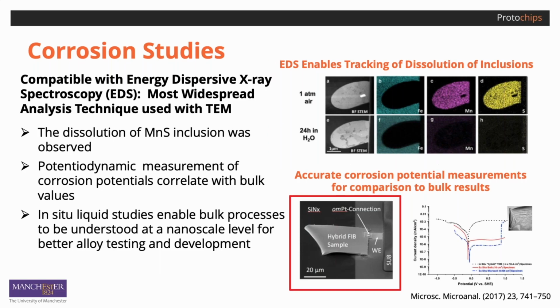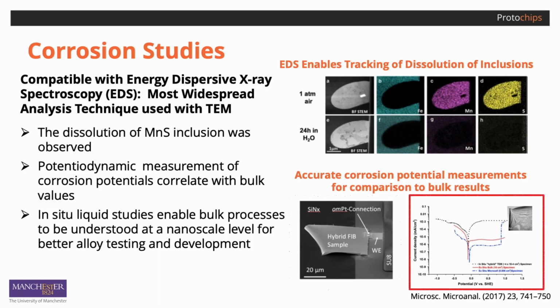An FIB section of type 304 austenitic stainless steel alloy is shown attached to the working electrode of the E-chip to enable measurements of potentiodynamic polarization curves in sulfuric acid for comparison to bulk data. The black curve was measured in situ using Poseidon, and the red curve was measured using traditional bulk methods. The peak for the corrosion potential correlates very well for both bulk and in situ data, with differences in current density attributed to the influence of charge buildup due to the electron beam.